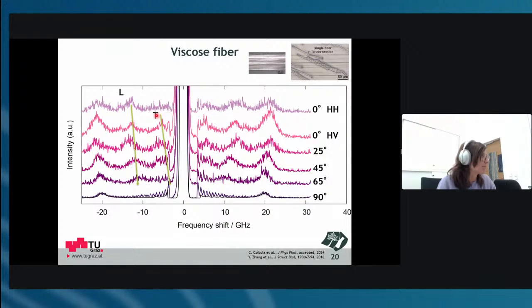And as it looked, there was no second transverse peak. They either overlap in this material, or it's not possible to resolve them because they're so close together. You will see that now on the next slide. And this is the backscattering signal that I was mentioning. In this case, for the determination of the stiffness tensor, it was an artifact for me. But it's still interesting to get this kind of new insight from such an optical measurement, because it's not just mechanics somehow.